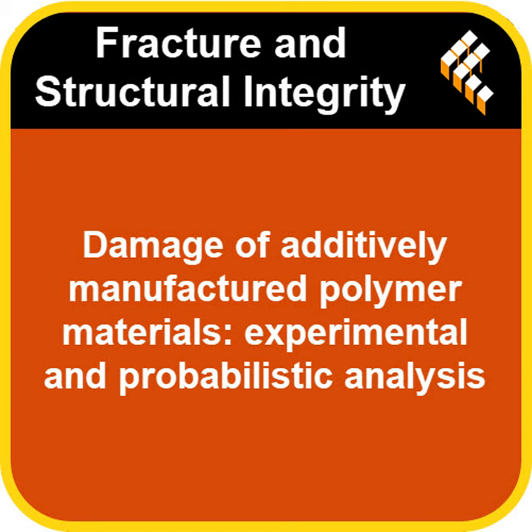Now, Miner's rule is a very common approach in structural engineering, isn't it? Especially for fatigue. It is. It's a relatively simple linear damage accumulation rule, widely used. And here's a practical takeaway from their analysis. The study suggested that Miner's rule actually provided a higher level of safety in this context. How so? Well, their specific application of the unified theory in this study seemed to underestimate the damage compared to what they actually observed in their static tests. So the unified theory model they used was maybe less conservative? Predicted less damage than actually occurred? That seems to be the implication in the paper. Which means Miner's rule, being more conservative perhaps, or at least aligning better with the static damage observed here, would lead to a safer design if you used it for predictions.